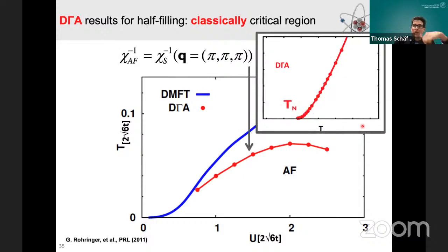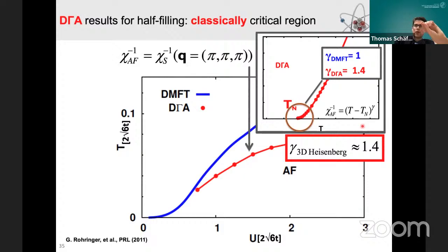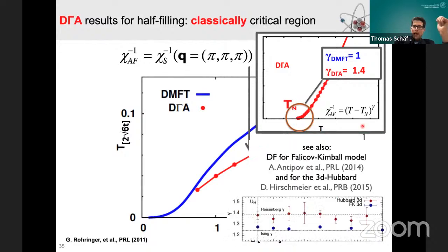If we now include spatial correlations, however, on top of DMFT, by means of this DΓA, we see that we get an alteration of this critical exponent from the DMFT value of 1 to the DΓA value of 1.4, which falls into the same regime as the 3D Heisenberg model. And this was later on confirmed also by other techniques.